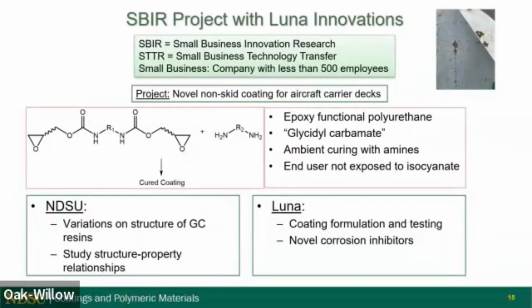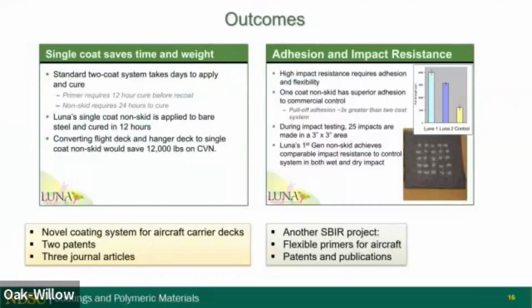So again, it sort of allowed us to do what we need to do as a university, which is training students, developing knowledge, publishing papers. But then we were able to come up with a really nice formulation. And so some of the outcomes of this were the previous system, or the current system, is a two-coat system that takes days. So the primer needs a 12-hour cure, the non-skid top coat 24 hours to cure. Because our technology is a little more reactive than the traditional system, they were able to develop a single coat that would cure and be ready to go back into service in 12 hours.